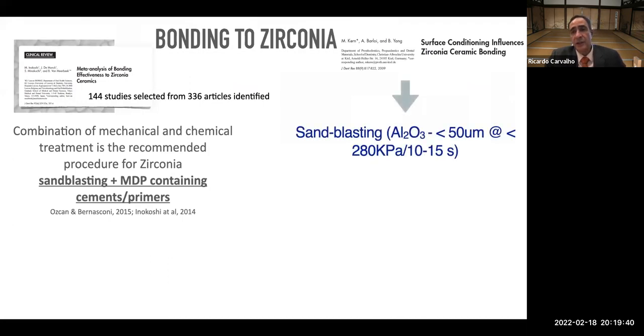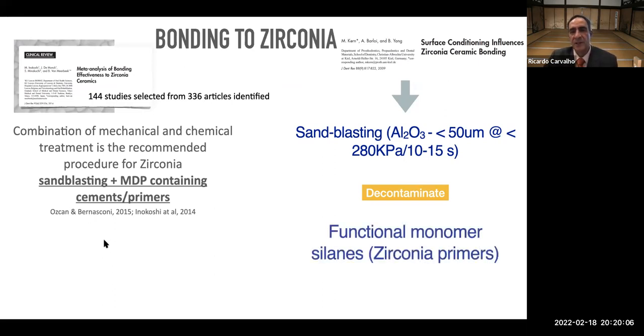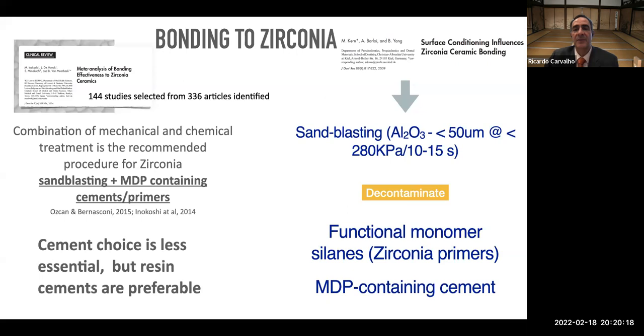So in summary, this is what we do. We sandblast with aluminum oxide particles, 25 microns or smaller than 50, at a lower pressure, 10 to 15 seconds to cover the entire intaglio surface. And then, of course, I will decontaminate the surface. So I did my try-in, I did my adjustments when necessary, and this is the final stage. Decontaminate, and then I apply functional monomers, which are not silanes, but functional monomers or zirconia primers. It's an analogy of the silanes we apply.